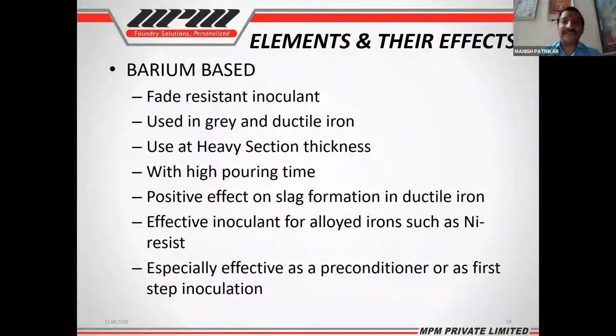So if we look specifically at barium, it's a fade resistant inoculant. It is mainly used in gray and ductile iron commonly. It's used at heavy section thickness also with a high pouring time, with a positive effect on slag formation in ductile iron, and is an effective inoculant for alloyed irons, especially effective as a preconditioner or as a first step inoculation. So these are the elements and their effects.